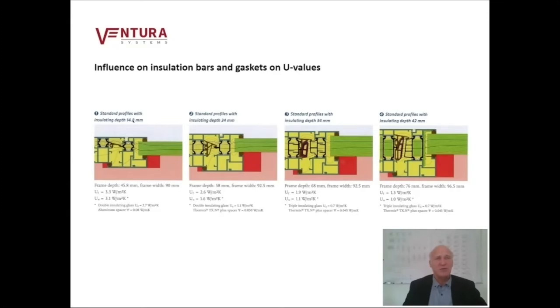We see there already SN3 triple glazed used. We see foam insulators, and we see a rebate gasket infill. These are all measures to improve U values. Important is that the Ventura V70 series with only 70 millimeter frame depth creates a UF value of 1.3, which is done with only 34 millimeter depth of insulators.